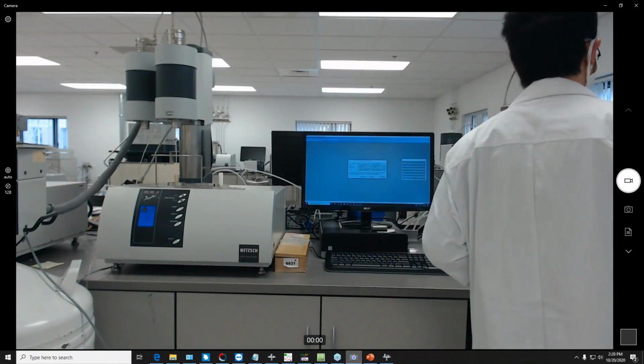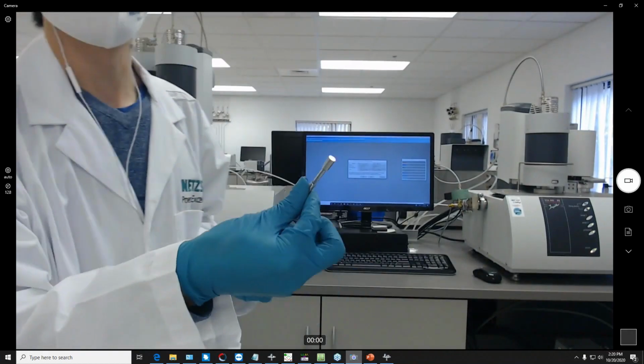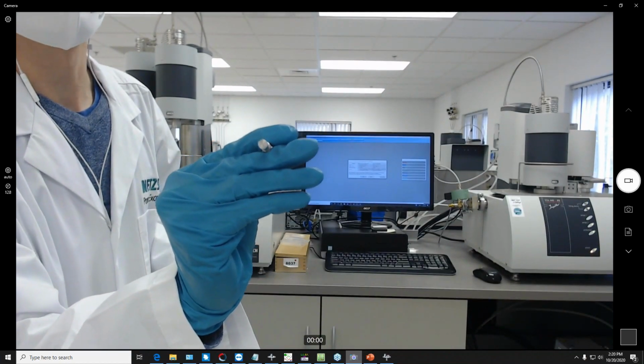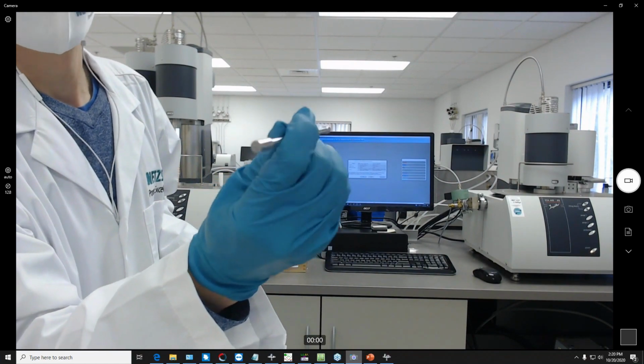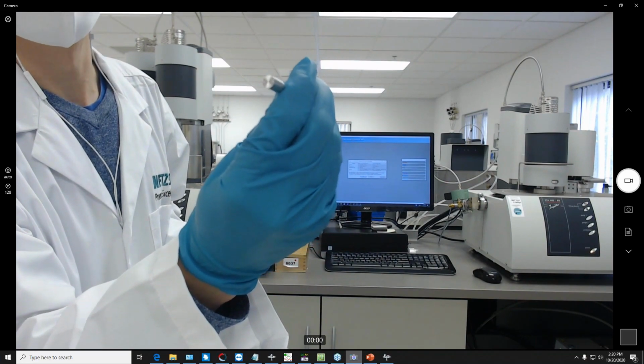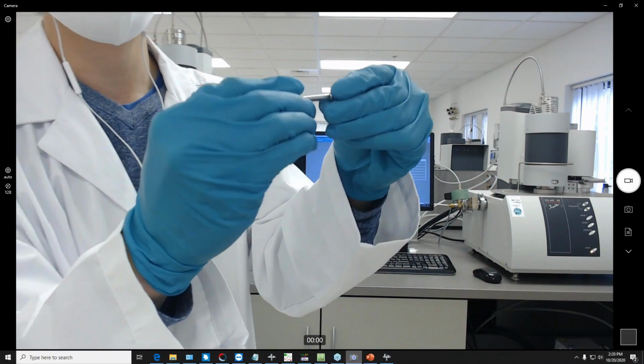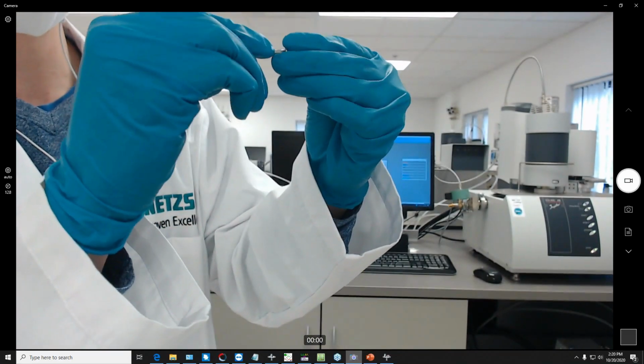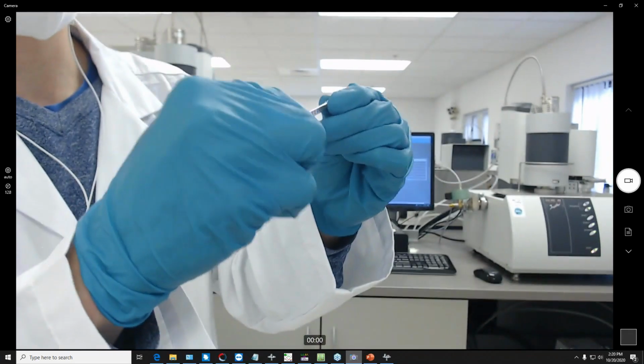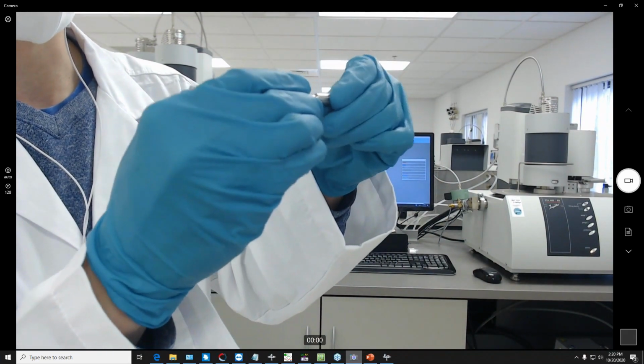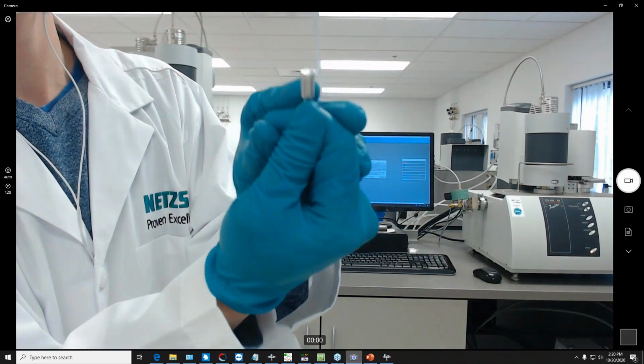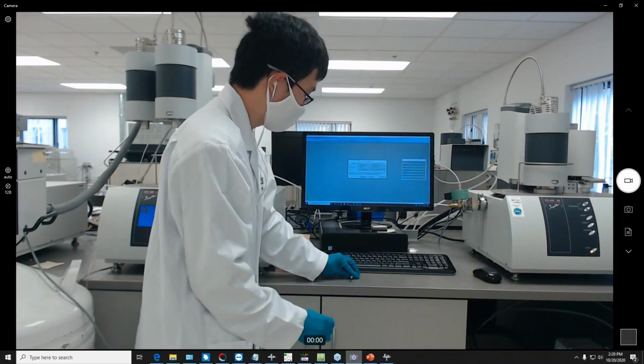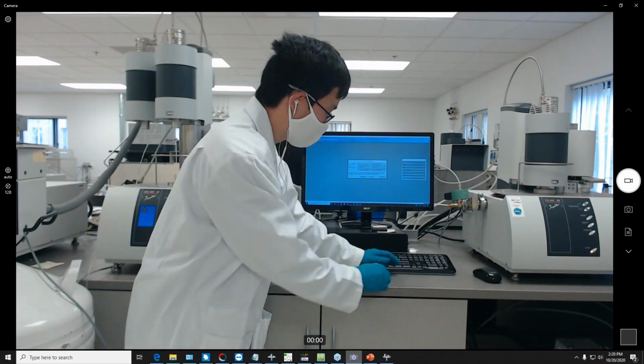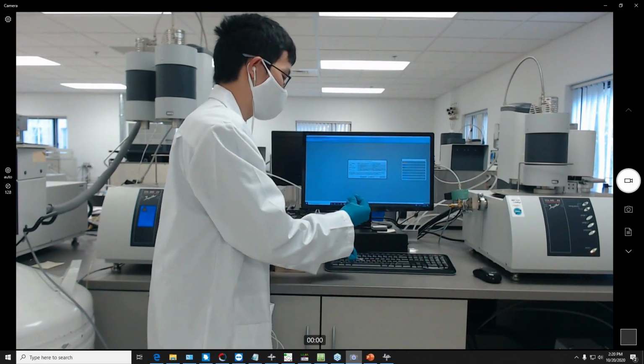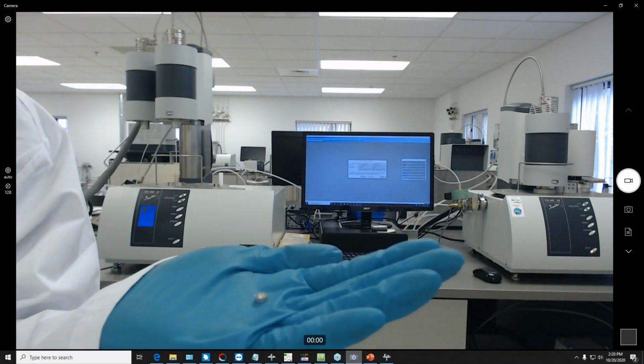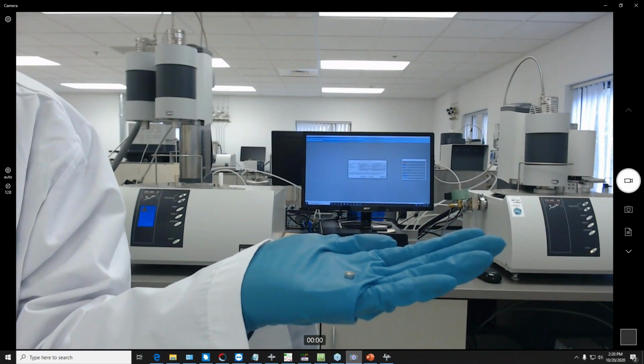So we have a crucible reshaping tool. It looks like this. On one end, it's a little bit skinnier, and on the opposite end, it's a little bit fatter. The fatter end will be the final shape of our round crucible. Usually we'll use the smaller, skinnier end to push the crucible walls back out, so that it's in an almost general round shape in which we can fit the fatter end over. Once I get the fat end over, I can go on a countertop and roll it so that it's nice and round again. Now I remove it, and I have a round crucible again where I can put a lid on it and run more experiments.